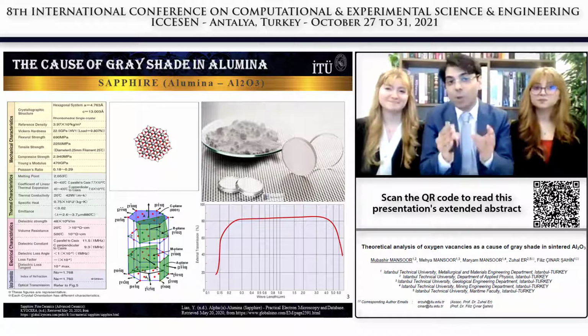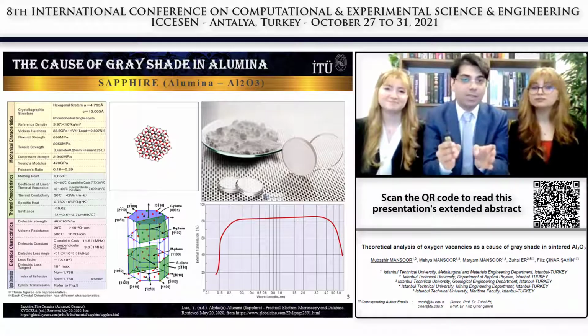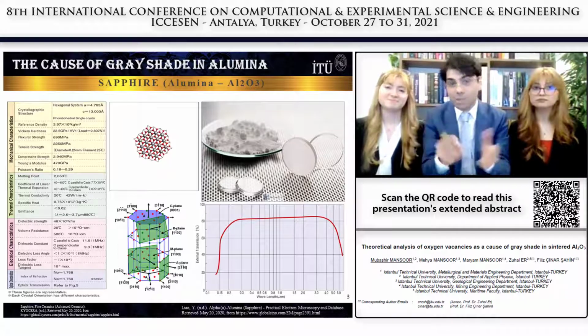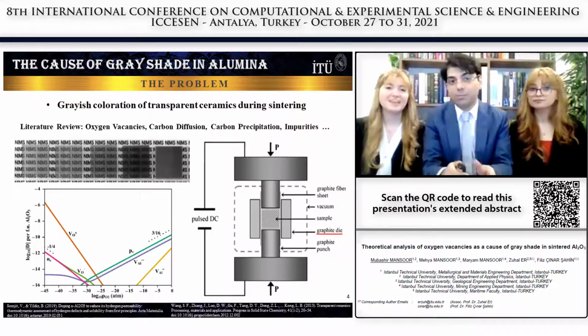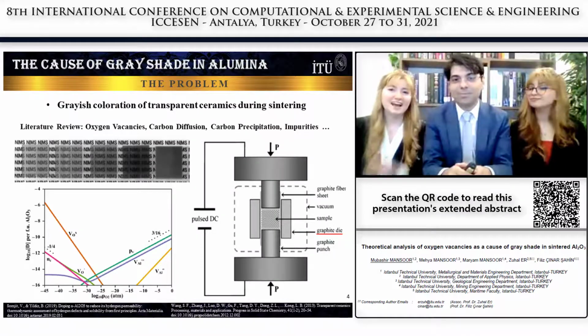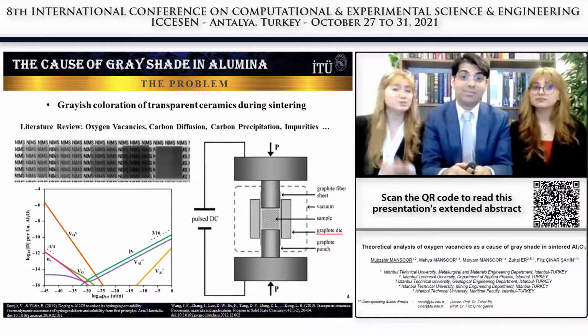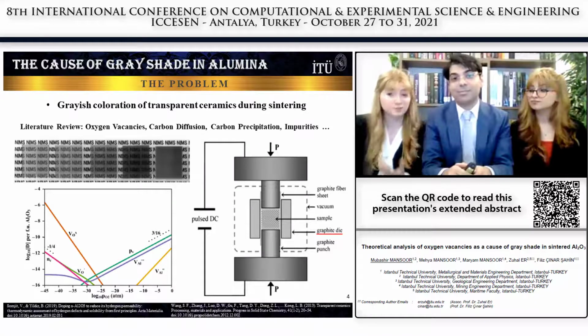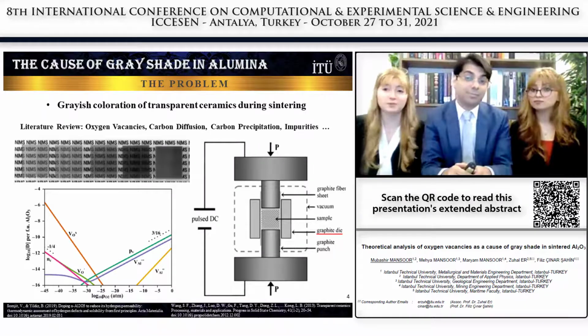Now, it is possible to sinter alumina powder to complete transparency under pressure using state-of-the-art methods such as spark plasma sintering. But there is a problem. The as-sintered alumina ceramics turn out to be grayish for some unknown reason. There are a number of possible theories when we look at the literature, the most important of which are oxygen vacancies, carbon diffusion, carbon precipitates, and impurities.